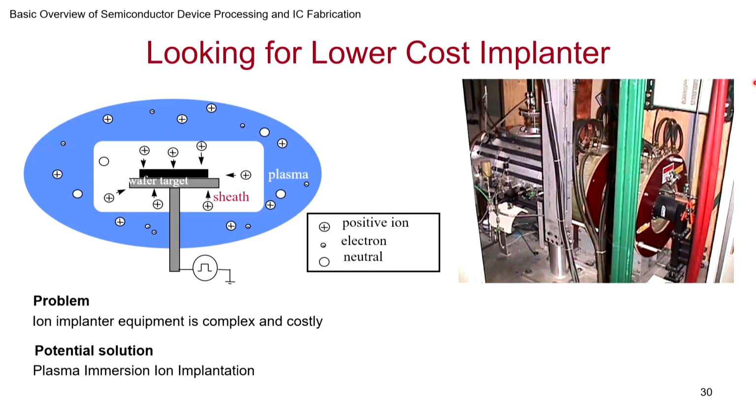So this is the general concept. You have a plasma. Plasma, as we know, is a soup of positive and negative, and usually the positives are ions and negatives are electrons, which are not in thermal equilibrium and going around in that. Now when the target is immersed in that and I apply a bias, what would happen? The ions will get accelerated, come to the sheath, and they'll accelerate through the sheath. The drop in the quasi-neutral region will be negligible. Most of the bias that is applied will be coming across this.